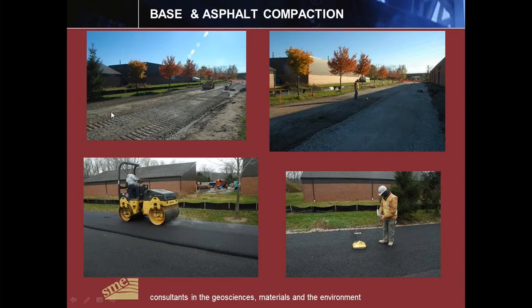Once the subgrade was stable by proof rolling, we cordoned off our sections, installed the lysimeters, and then placed our base course materials. Once the base was placed, we used a smooth drum vibratory roller to compact the materials to obtain their final densities, and then placed the asphalt layers over the top of them and tested the asphalt.